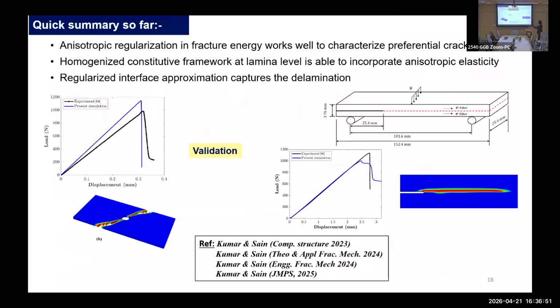So this is the part that we have already published, and if you take a quick summary of it, the anisotropic regularization that we have introduced in the gradient term of the fracture energy works well to characterize this fiber-oriented, preferential crack growth. The homogenized constitutive framework was used to incorporate the elasticity. And of course, the regularized interface approximation works well to capture the delaminations. And we have done quite rigorous experimental validation in the papers.